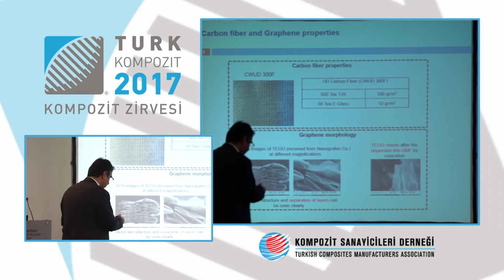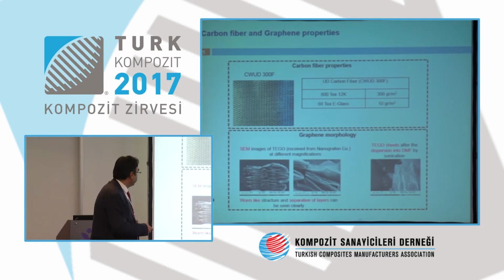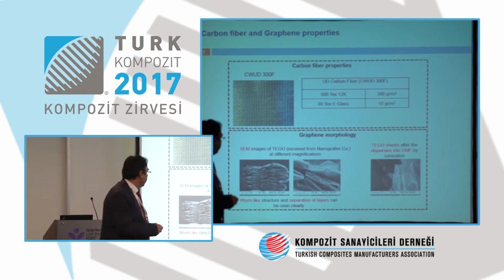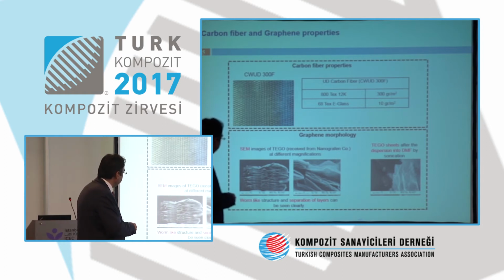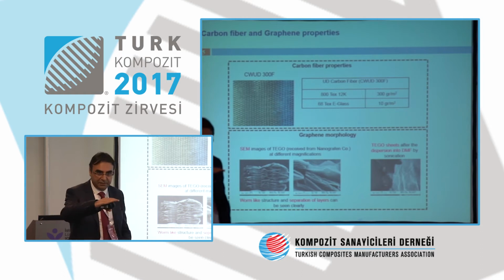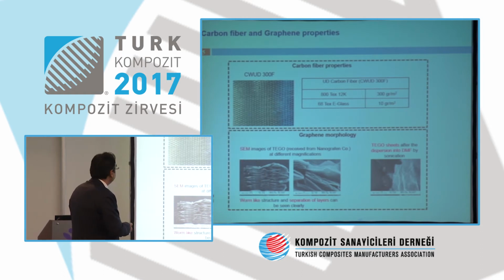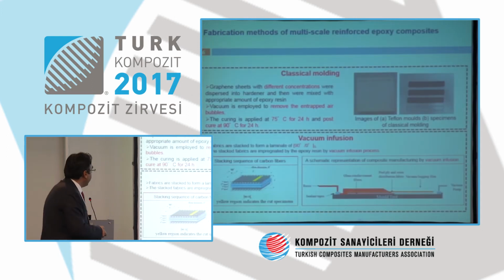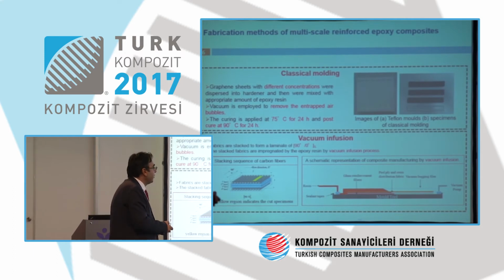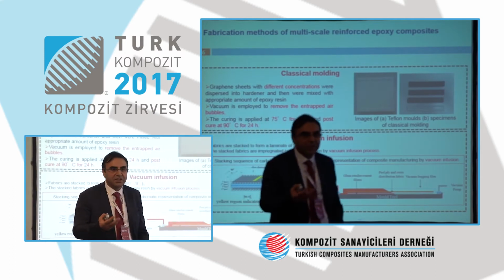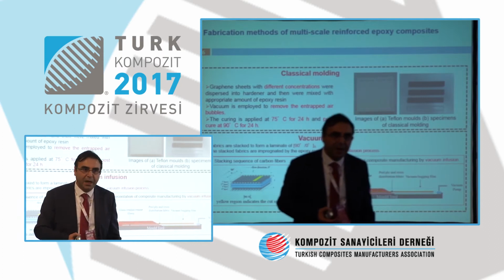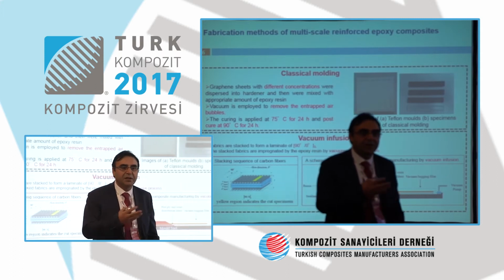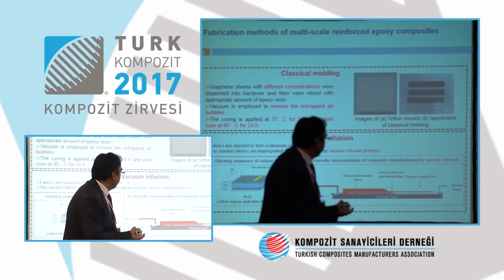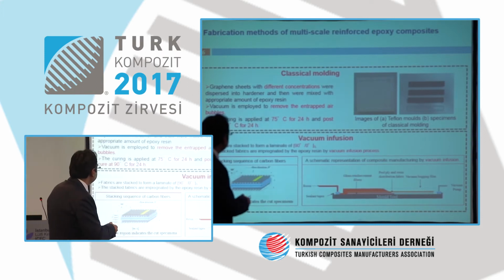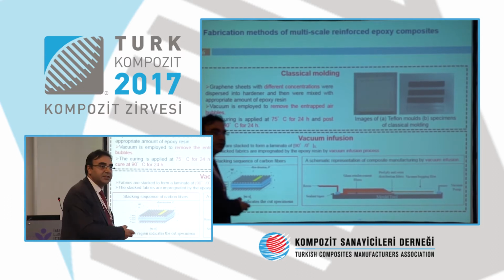And these are the graphenes that we produce at the center. Now we have a spin-off company called Nanographene that can produce thermally exfoliated graphene, which is formed by multiple layers. If they can be sheared, they can be reduced into a single sheet, so that you can increase the surface area of the material. And what we have done is that first we try to improve the mechanical performance of the resin. We just mix them, by functionalizing the graphene properly with the epoxy resin, and then under a high shear mixer, we make a classical molding. And later on we integrate it into the composites, into the matrix as well.